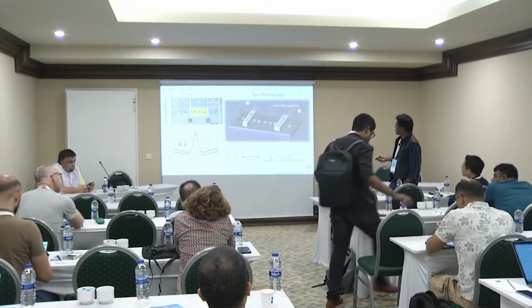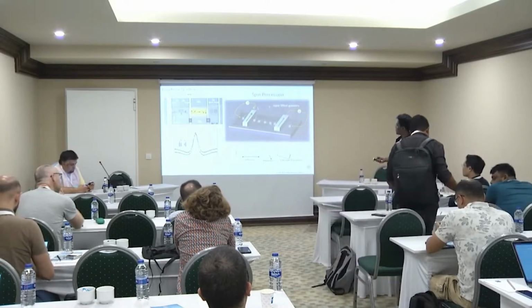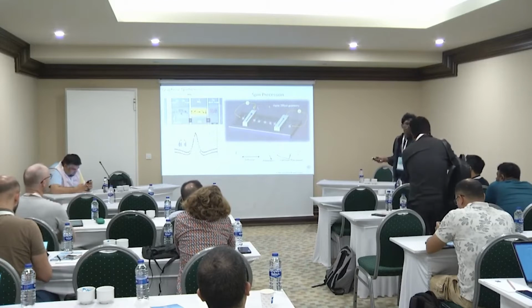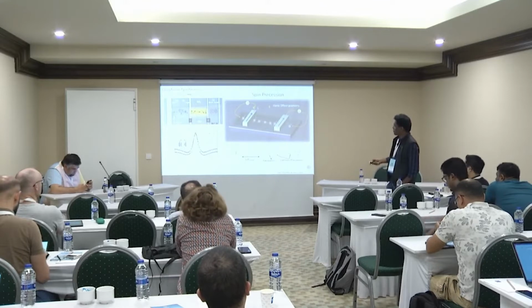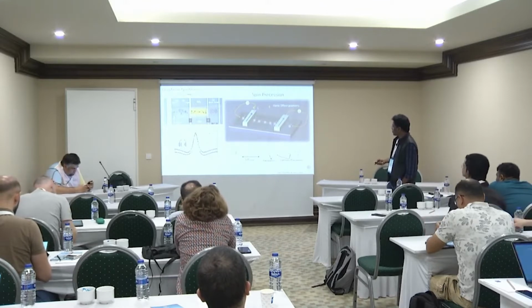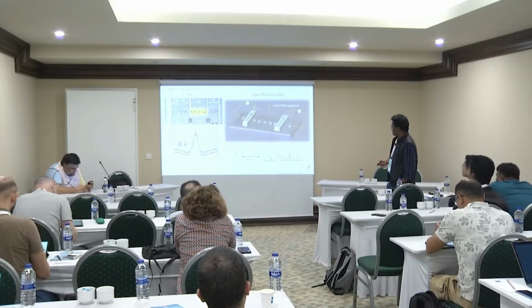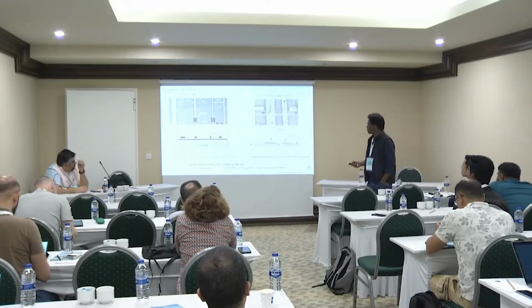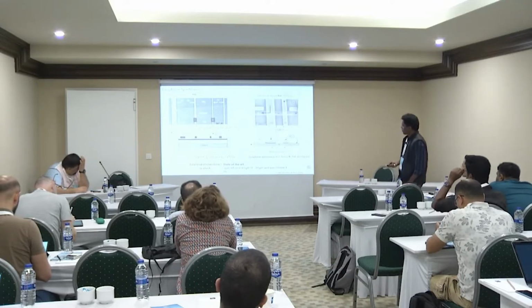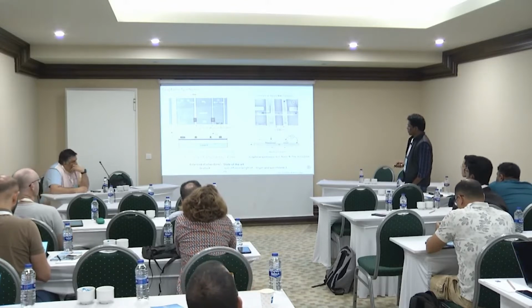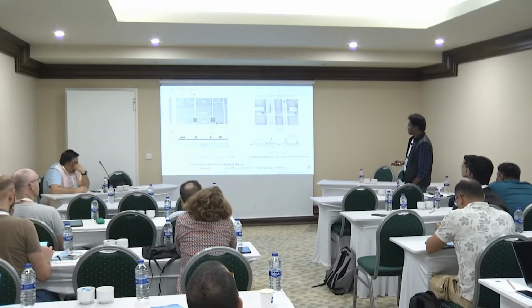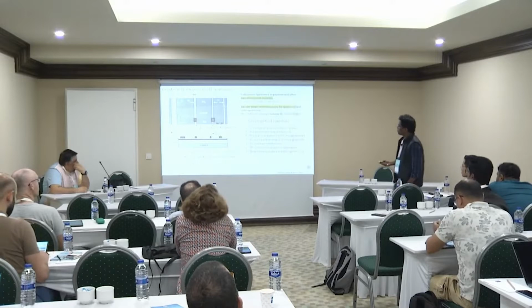In case of spin precession, a perpendicular magnetic field is applied, whereby the electrons precess about the magnetic field, and there is a continuous change in the spin signal, which can be fitted to an equation that contains a diffusion part, a relaxation part, and a precession part. And from there, the spin lifetime can be determined. So a lot of attempts have been made, and state-of-the-art reports say today that a spin diffusion length of 10 micrometers and a spin lifetime of 1 nanosecond can be achieved in graphene spintronics.